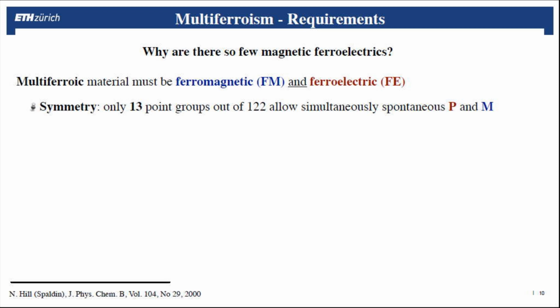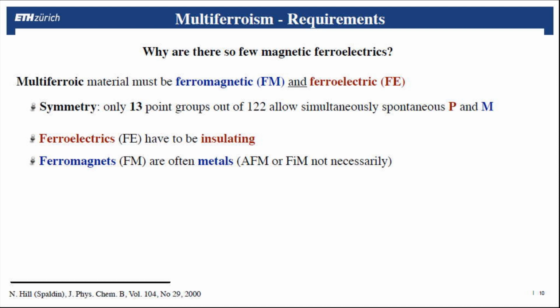If we consider symmetry, just meaning the positions of your atoms in the crystal, you can find that out of 122 possible symmetry systems, only 13 would allow simultaneously a spontaneous polarization and a spontaneous magnetization. So that's already not a lot of combinations that are possible. Then to have a ferroelectric material, you should have a material that is insulating, because if it's a metal, then you would have charges floating around and you could not have a net polarization in the material.